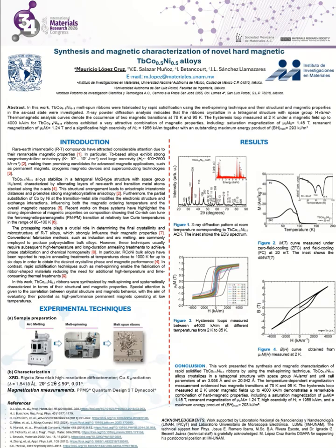and remanent magnetization of 1.24 teslas, and a high remanence ratio of 0.86. This value exceeds the theoretical limit of 0.5 predicted by the Stoner-Wohlfarth model for randomly oriented particles, suggesting strong magnetocrystalline anisotropy and possible texture in the ribbons.